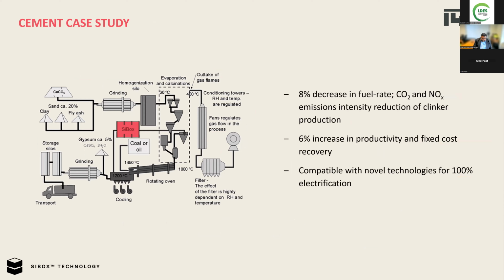Again, a very high temperature industry where roughly about 20 to 30% of their CO2 emissions is fuel related. Remaining is process emission, which comes from the calcining of the carbonates. So in this process as well, you can integrate a SIBOX in a retrofit configuration and decrease the fuel rate by up to 8%, and hence also reduce the CO2 and the NOx emissions from the calciners. Another interesting feature over here is that when you reduce that NOx emission intensity, the ammonia use, etc., for catalytically disrupting the NOx emission also goes down. So it has operational advantages to integrating with the thermal storage.